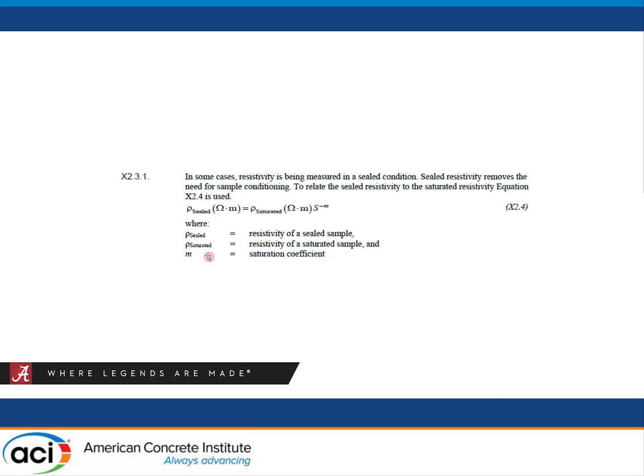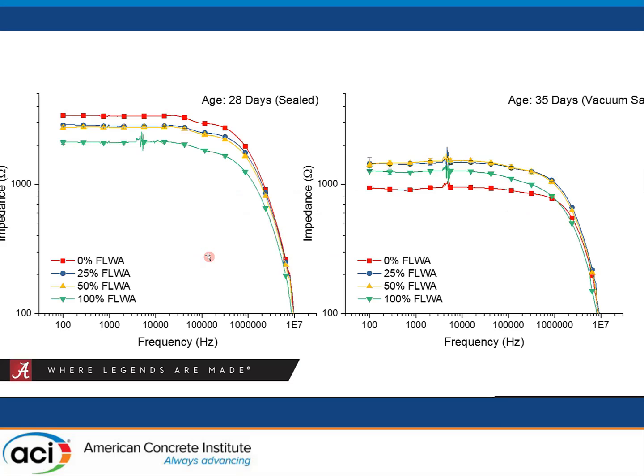And so when you have the lightweight aggregate, you have almost an order of magnitude higher porosity in that aggregate as you do normal aggregate, like a silica sand. And so that brings into question, all right, is that 3 to 5, or is that type of saturation coefficient, applicable to mixtures that have saturated lightweight aggregate? And then additionally, what might be the age effect of this? And so that was kind of what we were going on to study.